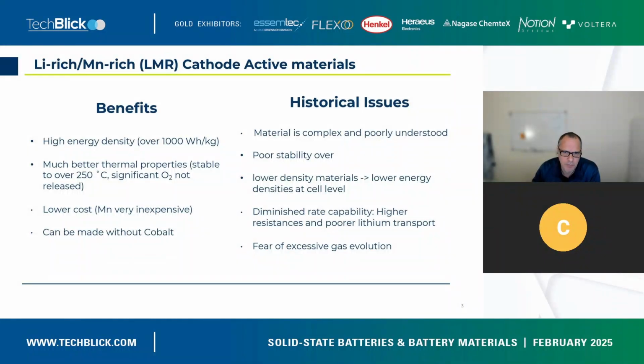It typically has poor stability over tens or hundreds of cycles. And that stability challenge is typically similar to what is seen in the disordered rock salt system, in that it oftentimes will collapse into a spinel phase that has about a 3-volt plateau, and that in general can lead to other structural issues and manganese dissolution as well. So you don't really want that collapse to that spinel phase if you can avoid it. And the materials often are lower energy density, lower physical density, because carbonate precursors are frequently used to produce it. And that gives you lower watt hours per liter at a cell level. And that's always been a challenge as well.